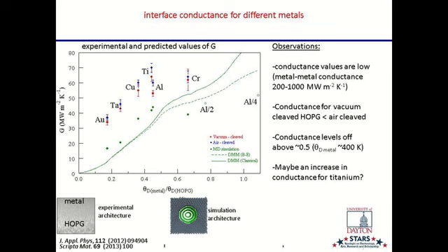We did some simulations and some very fundamental measurements of thermal conductance. And we did it for some elemental metals and also for some metals that react with carbon surfaces, that are very reactive. And what we found is that we can understand how these metals improve interfacial thermal conductivity by understanding their vibrational properties. So these are some Latin or Greek letters, but really this is representing how well we're matching the vibrational properties of the nanotubes with the metals that we've selected.